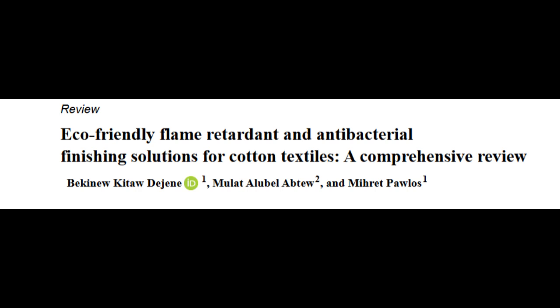What did the study show? Really impressive results in the lab. Fabric treated with herring sperm DNA, that was the source used, self-extinguished in tests, burned slowly, had a much higher LOI than untreated cotton, and didn't even ignite under certain heat flux conditions. That's incredible. Why aren't we using it then?